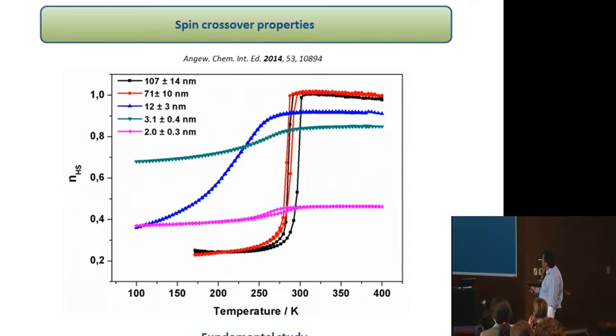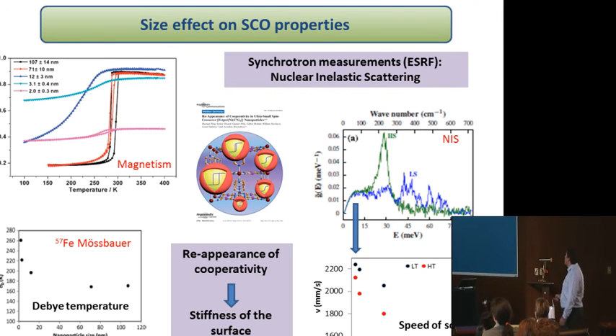This is very new and not expected for these 2 nanometer nanoparticles. This was predicted by theoretical calculation, but for the first time, it was possible to observe that for such small nanoparticles, we observe a re-increase of the cooperativity, since we observe a hysteresis loop for these 2 nanometer spin crossover nanoparticles. Of course, the percentage of transition is small because you have only less than 100 iron centers in this case. Okay, so this was predicted by calculation, but we wanted to confirm that.